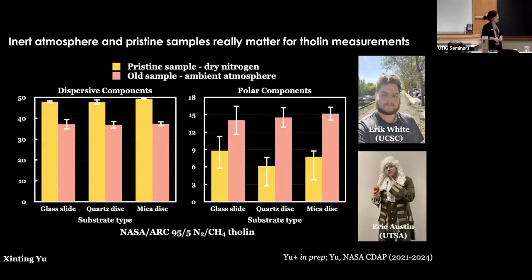So my student, well, I have two Erics, which are both amazing, but we did a measurement comparing a pristine Titan haze sample that's never been exposed to air, and a sample that's been exposed to air for maybe a few weeks. And we found everything changed. The surface energy changed, the chemistry definitely changed, because the dispersive component and the polar component all changed. We tried different substrates, but the substrate effect is nothing. It's just whether the samples are exposed to the atmosphere.